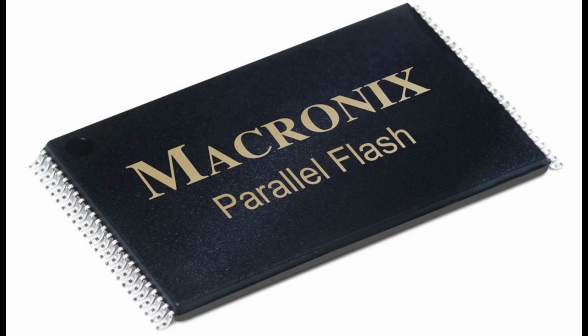The FG is interposed between the CG and the MOSFET channel. Because the FG is electrically isolated by its insulating layer, electrons placed on it are trapped. When the FG is charged with electrons, this charge screens the electric field from the CG, thus increasing the threshold voltage (VT) of the cell. This means that the VT of the cell can be changed between the uncharged FG threshold voltage (VT1) and the higher charged FG threshold voltage (VT2) by changing the FG charge.